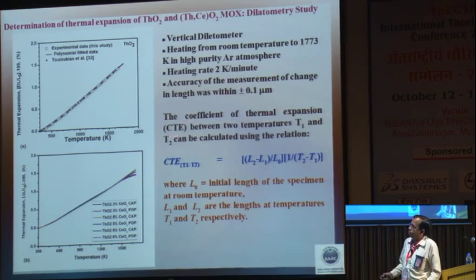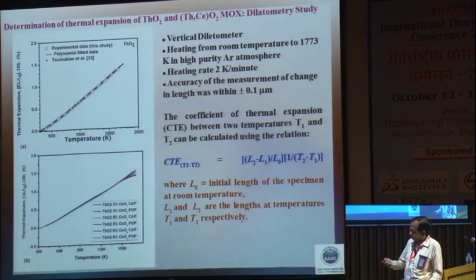The coefficient of thermal expansion has been evaluated by this equation, where L2 and L1 are lengths at two different temperatures, T1 and T2, and L0 is the initial starting length. So with this, the thermal expansion has been evaluated both for thorium oxide, as well as the mixed oxides which are developed here, and you can see that there is no big substantial difference in the values irrespective of the fact that it does contain the other element as well. And these values also agree very well with the earlier attempts of such a determination by this group of workers.